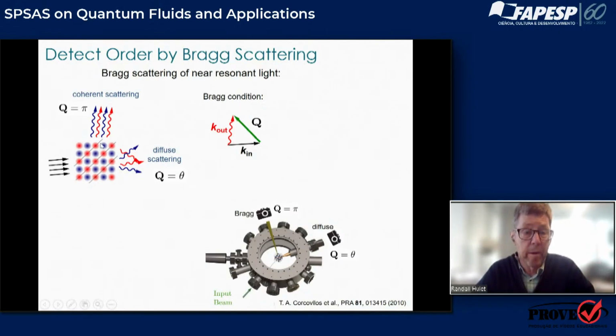And so here's our crystal lattice shown in 2 dimensions. It's actually 3. But you have light incident on this lattice at a certain angle, the Bragg angle. And if there are correlations that have developed, you will see light scattered coherently at a particular angle. And the Q equals pi angle refers to the lattice vectors that one needs to match via the Bragg condition to the incoming wave vector determined by this incident light. And once you do that, you get coherently scattered light, represented here as either scattered light from the up spins or, in blue, from the down spins.